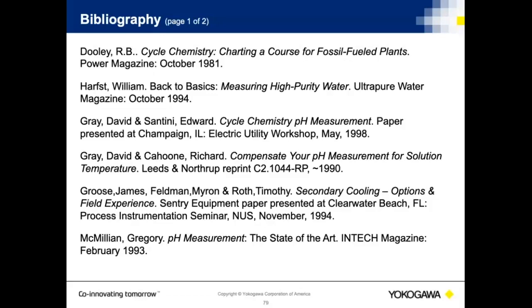Okay, next question: is it more accurate to take a pH reading at a process temp of 154 Fahrenheit or to take a grab sample and cool it? If you wanted to look at the technical nature of it, it doesn't really matter if you cooled the sample off. It's more to the point that if you're going to be making that 150, 160 degree measurement, to do the measurement right there at the point that you're making the measurement. As for the cooling of it, as long as it's cooled to a specific value, you should be all right. But then you have to worry about, did you cool it consistently to the same value? And then you have to worry about, was there any of this issue associated with the solution temperature compensation? And that you really can't tell unless you do the test.